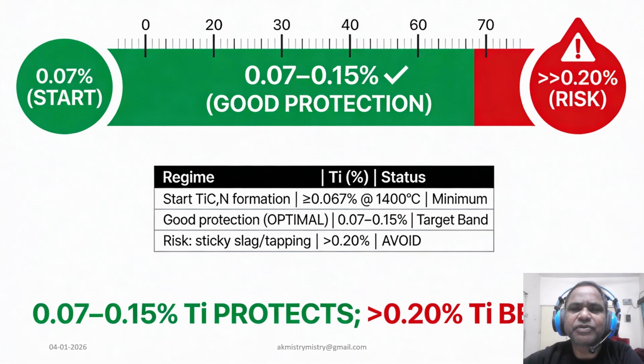Success also depends on staying within the correct target band, as is very nicely shown. For good protection we aim for a titanium concentration in hot metal between 0.07% and 0.15%, while the formation begins at 0.067%. You must be cautious of the red zone. If titanium level exceeds 0.20%, you risk creating sticky slag and difficult tapping conditions, a state we must avoid, and everyone must be aware of this boundary.